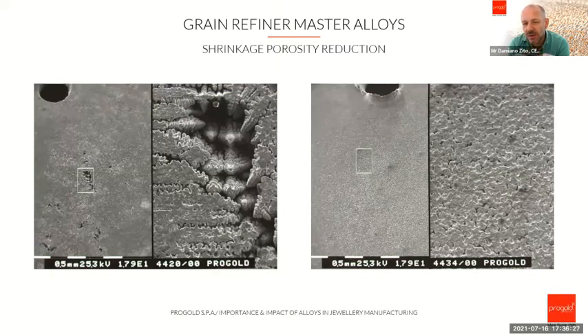That's why having a small grain size alloy helps with an unwanted effect that sometimes is not possible to avoid, because it's not possible to put the proper gate, or the proper size of the gate, or the shape of the jewel doesn't allow it. Then you have to face the problem of having some shrinkage on the piece that you are producing. The more spread the volume of shrinkage is, the more probable it is that you do not have to reject that piece.